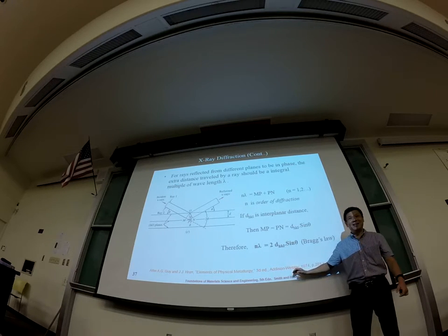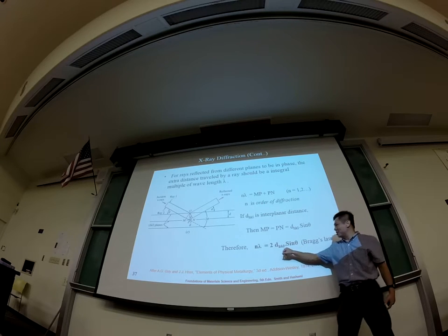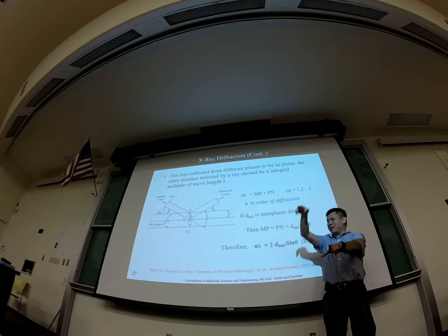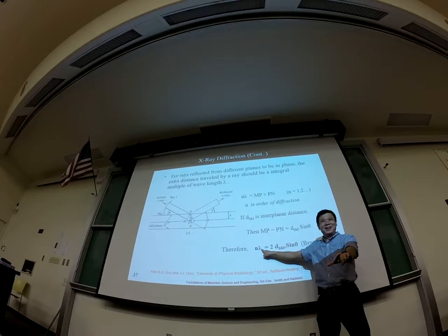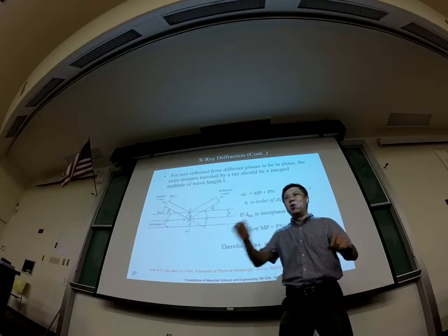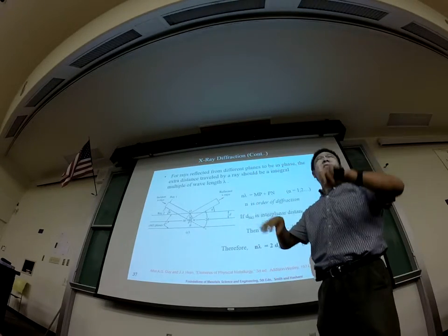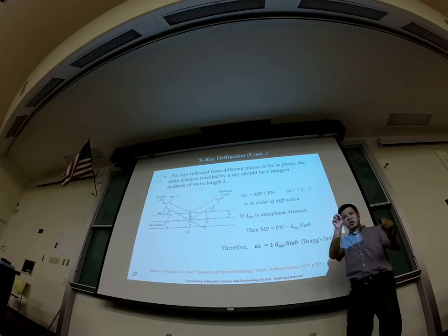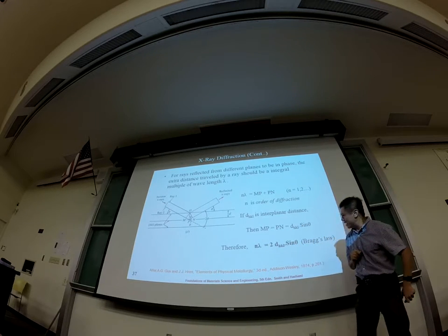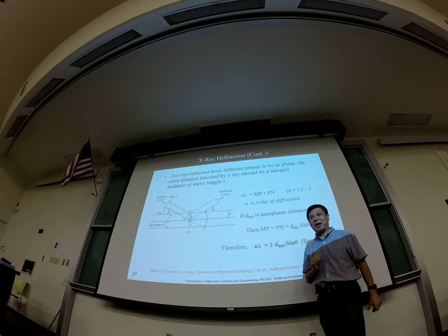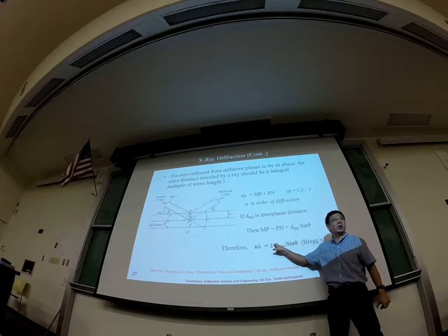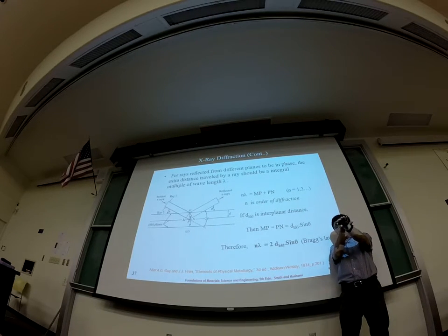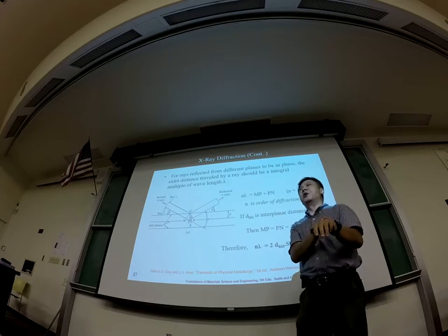You can change the angle. Yeah, you can change the angle. For those larger ones, do you need a small angle or a large angle, supposing the wavelength is a fixed number? Small angle. So we call that small angle X-ray, or SAXS. It's a widely used technology, called small angle X-ray analysis. Using it, we can even explore hundreds of nanometers, but the angle needs to be very small, 0.0-some degrees.